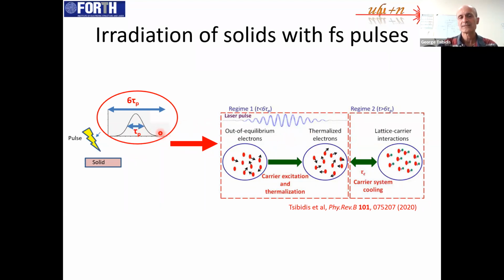So in the second regime, after the pulse ends, we have the electron-phonon coupling. So the electron system interacts with the lattice system through scattering, and gradually the two baths, because we can envisage the systems as two baths, the electron system and the lattice system, exchange heat, they exchange energy. So we have a relaxation state when the energy of the electrons is transferred to the lattice system.